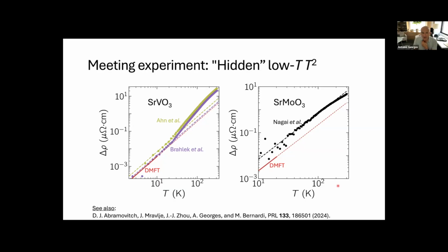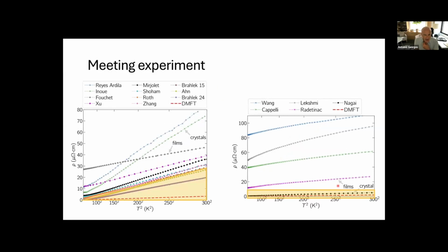Great. Thank you. If there are no further comments, maybe I still have a minute to make one. As you see, especially from the previous slide that you just showed, the experimental situation, especially for strontium vanadate SrVO3, is still very confusing, and especially the single crystal versus thin film situation. There is even an additional single crystal measurement that is not on this plot, and that adds to the overall scatter. So if there are experimentalists in the room who would be up to the challenge of cleaning up that situation, that would be wonderful. That requires excellent samples, obviously. Seconded.